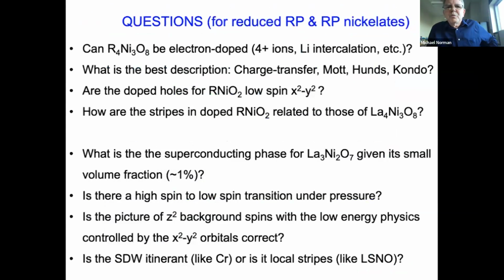So let me end with some questions here. Thinking about the reduced Ruddlesden-Popper states, where you're going towards the cuprate side of the phase diagram, one big question is, can the trilayer material be electron doped? The nice thing about the trilayer material is you can make very, very nice single crystals of it. It's been a challenge to electron dope it. You can think about replacing the rare earth by some sort of 4+ ion, or intercalating lithium. People have tried to do this. It's very challenging, so to date, not a success, but people have been trying.